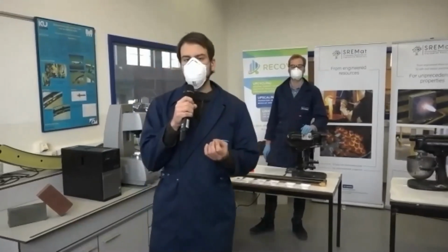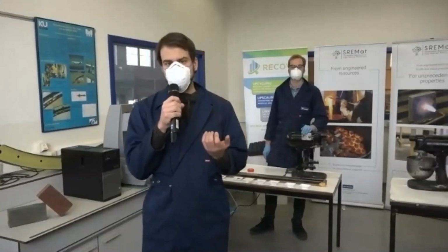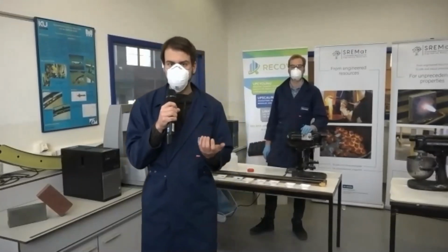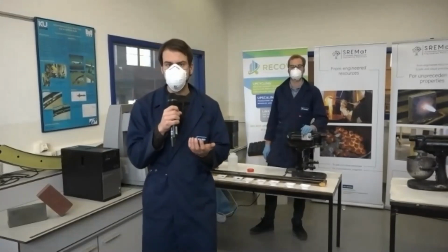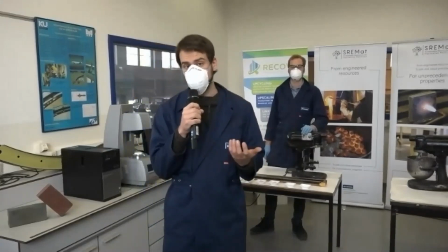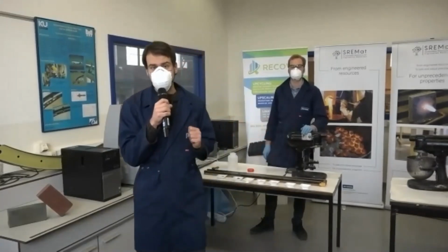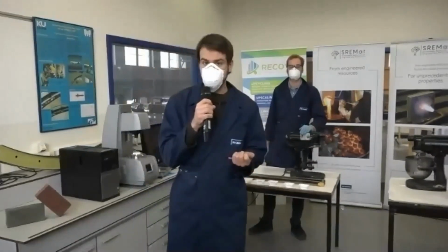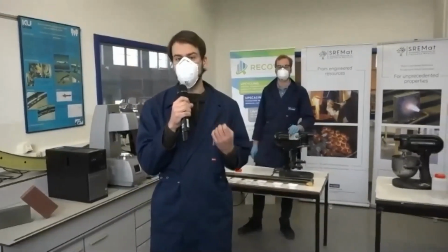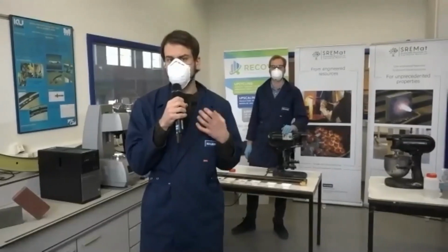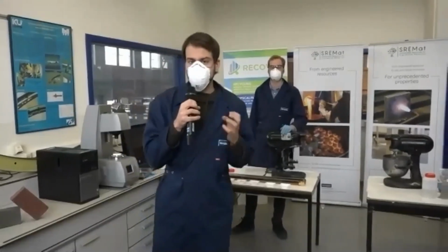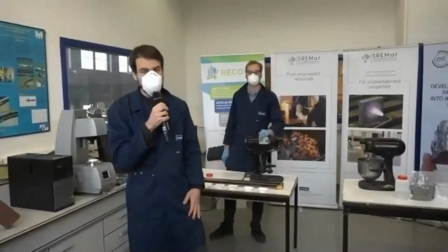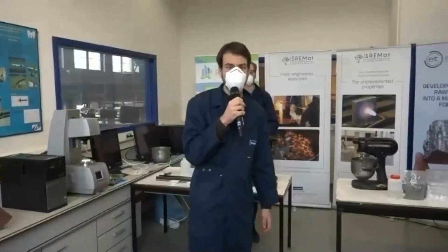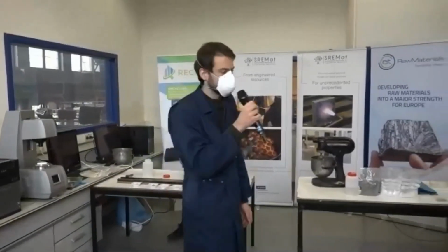When we use these inorganic polymers, we need to add normally an alkali silicate activator, which basically dissolves this slag and forms after a while an inorganic polymer. Roberto will present a specific type of an inorganic polymer, a so-called porous inorganic polymer. So we want to have a porous material with pores in the matrix, basically. So I hand over to Roberto for the presentation of these porous materials.